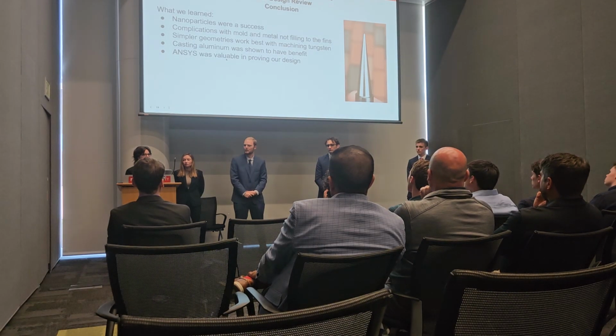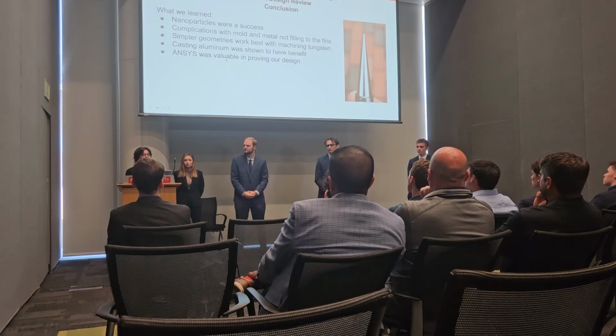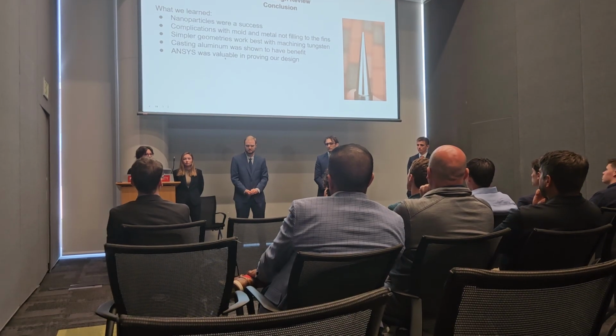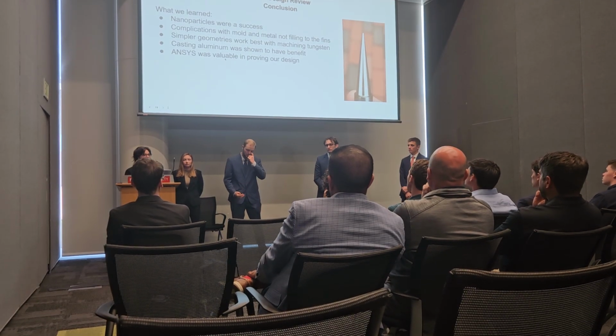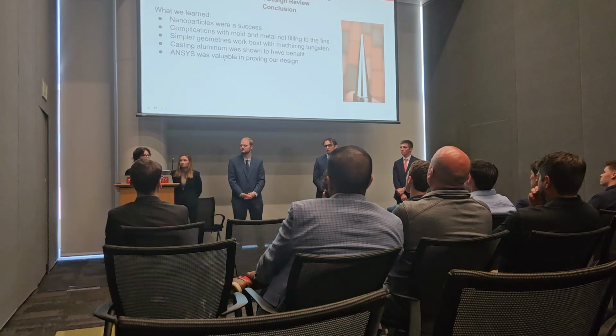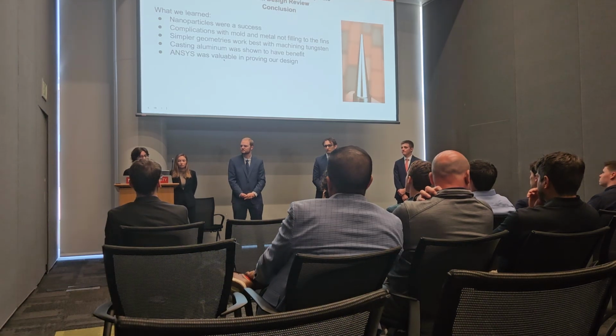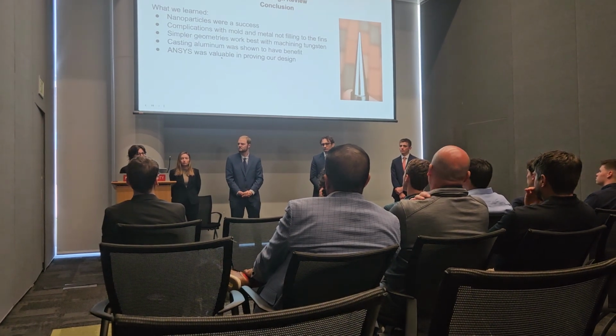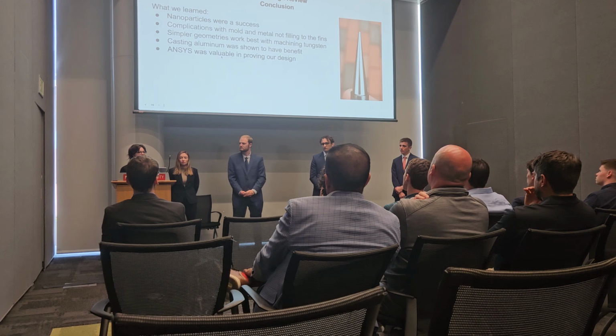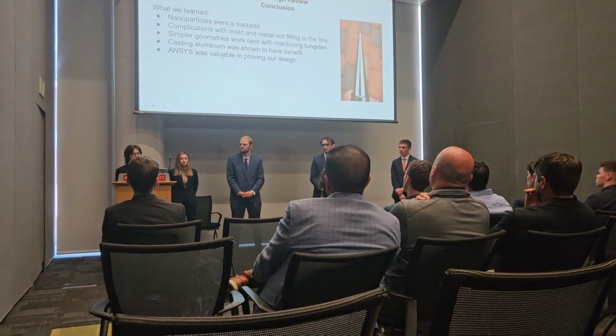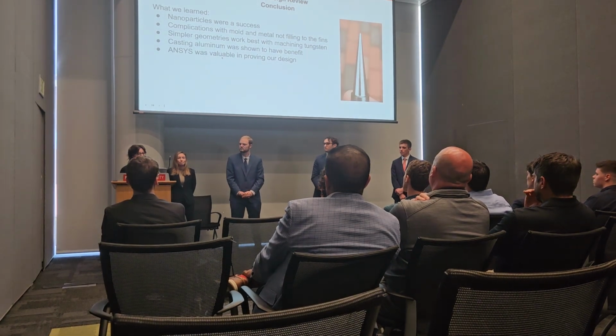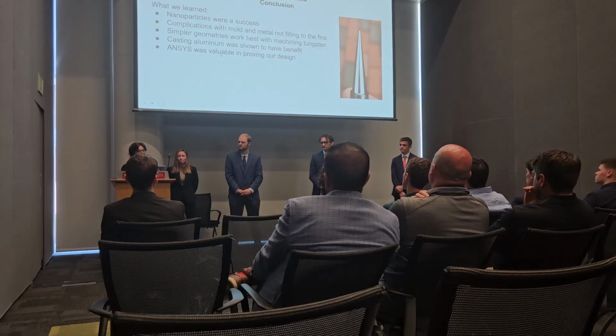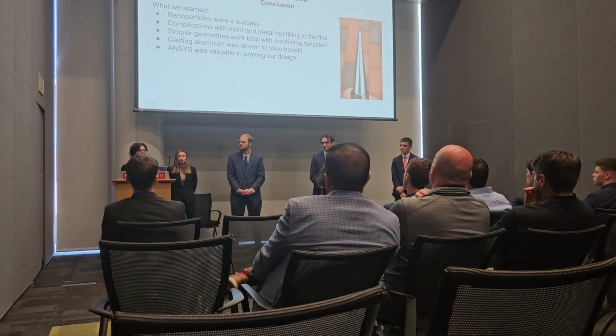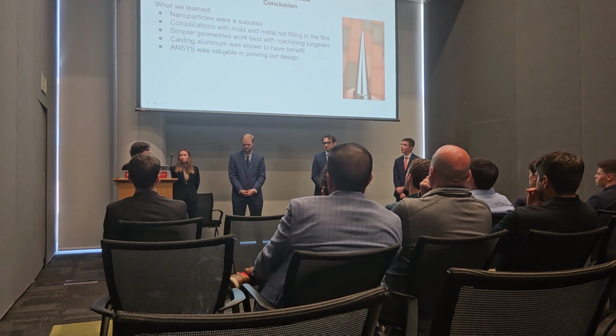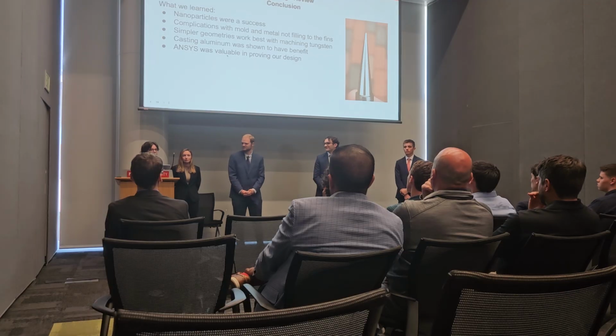We do believe that if we had access to a vacuum chamber that could withstand 900C, we would have been able to properly produce our fins and therefore have a fully functional projectile. We ended up using simpler geometries in order to machine our tungsten tip, as you can see here in this photo. We used ANSYS in our design in order to properly see how it would function, and we believe we did pretty well. Any questions?